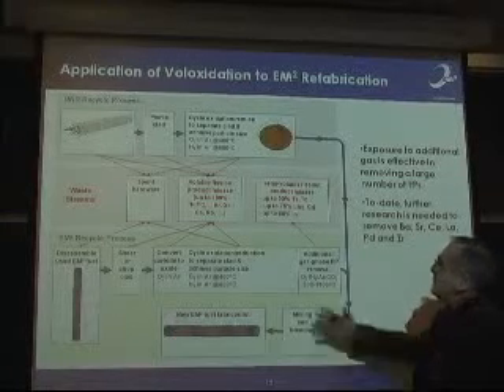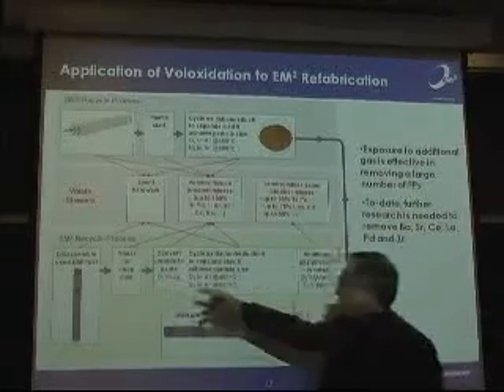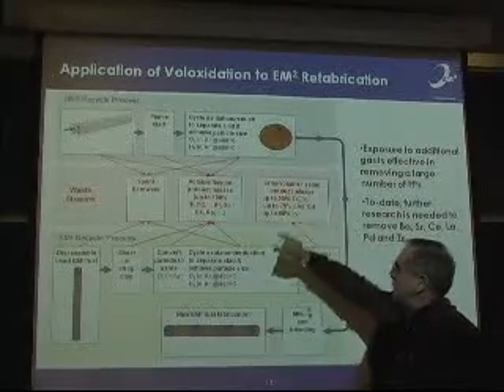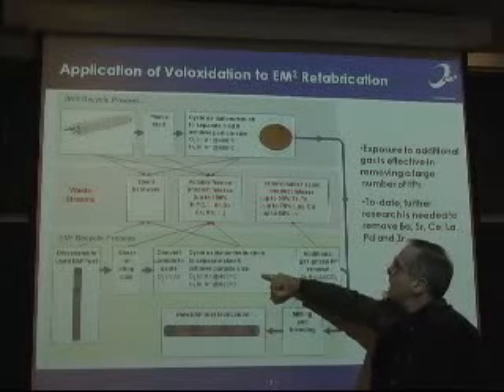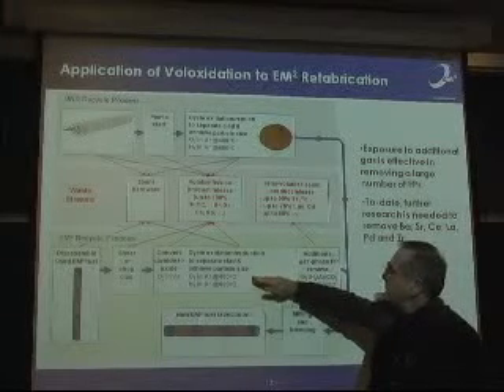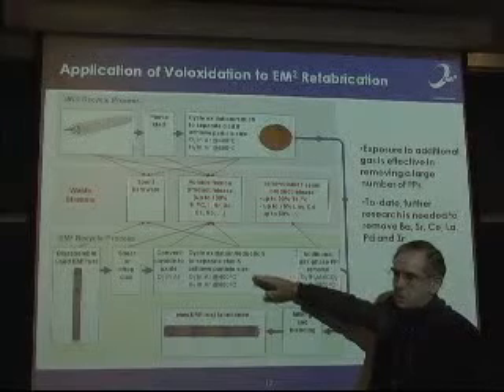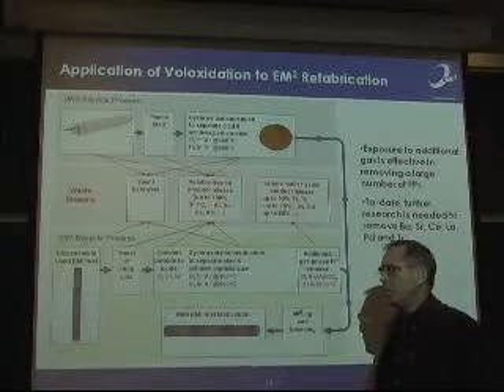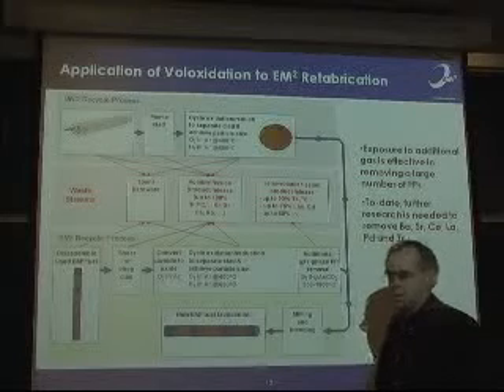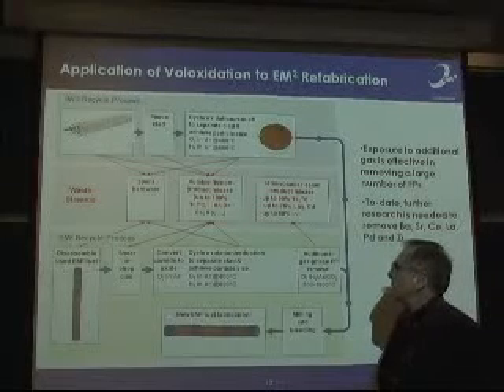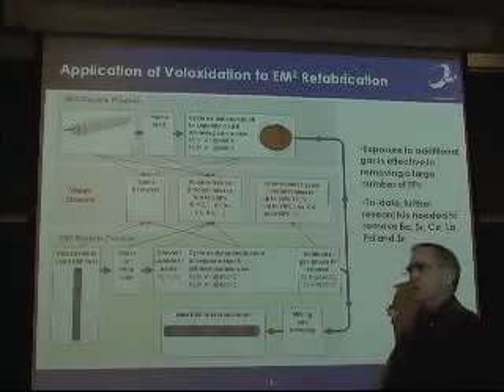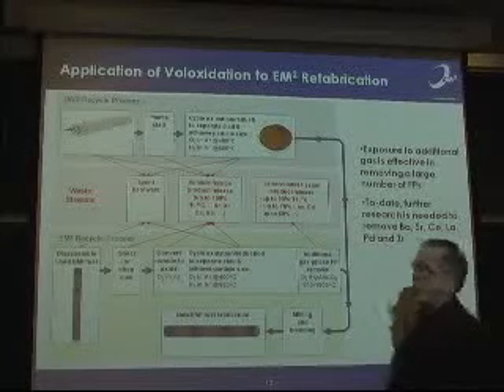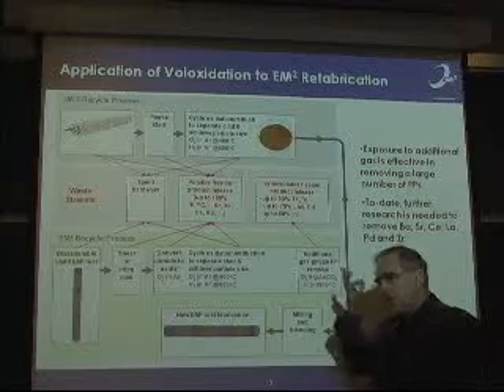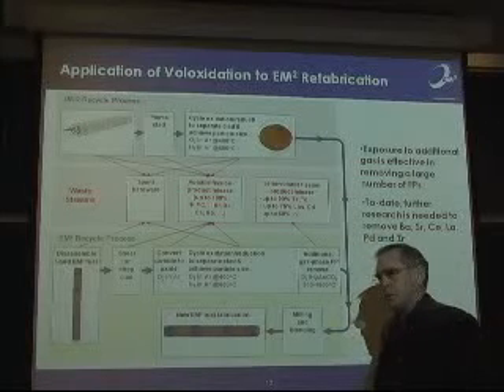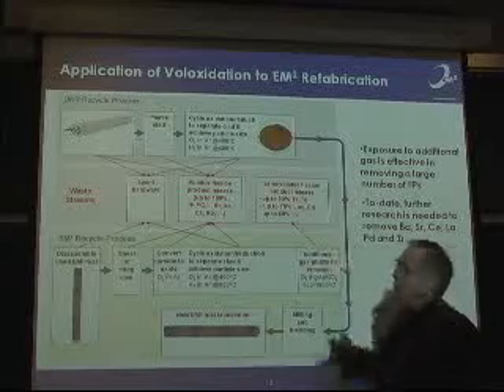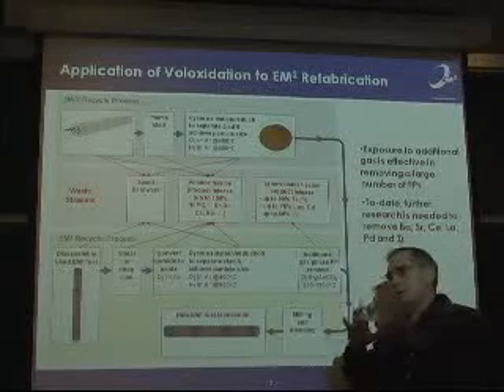And we can do essentially the same thing with recycling our own fuel by this Aerox process, but there's one feature here: we do need to take out about 60% of the fission products, and it has to be pretty well distributed over all the different species. So we have to add other gases besides just oxygen and hydrogen to try to extract those fission products out in a gaseous process.